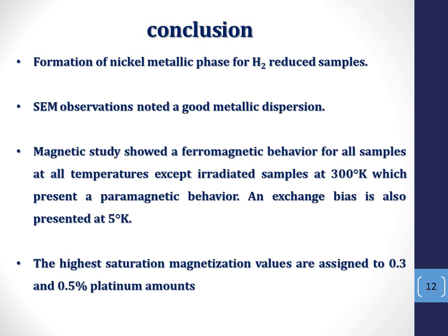In conclusion, there is formation of a nickel metallic phase for hydrogen-reduced samples. SEM observations noted a good metallic dispersion. The magnetic study showed a ferromagnetic behavior for all samples at all temperatures except irradiated samples at 300 Kelvin, which present a paramagnetic behavior. An exchange bias is also present at 5 Kelvin. The highest saturation magnetization values are assigned to 0.3 and 0.5% platinum amounts. Thank you for your attention.